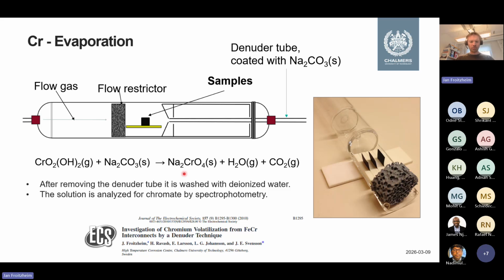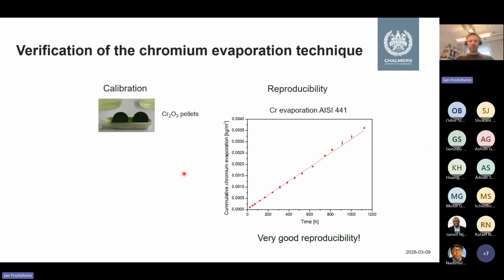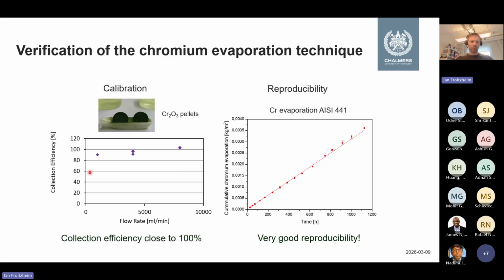So we developed that quite a while ago, and I'm using it quite frequently, and some other labs have also started to use this. To verify this, we used chromia pellets that were weighed before and after the experiment. And so the weight loss of the chromium pellets should correspond to the amount of chromium we find in our solution. And that actually works.